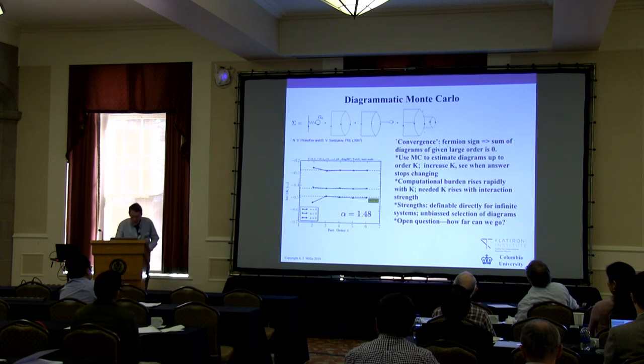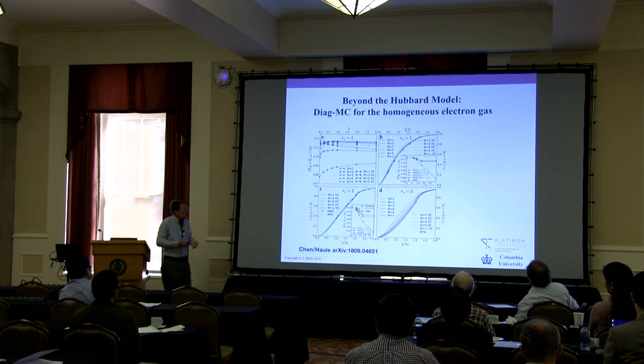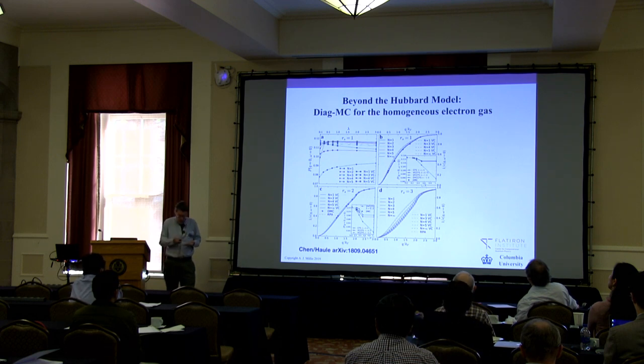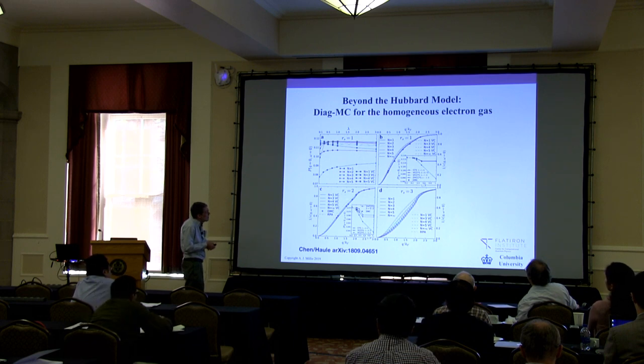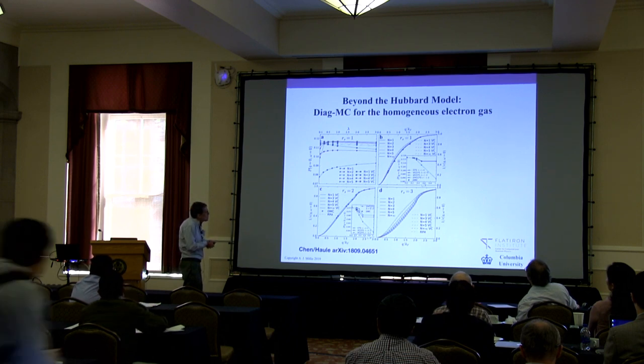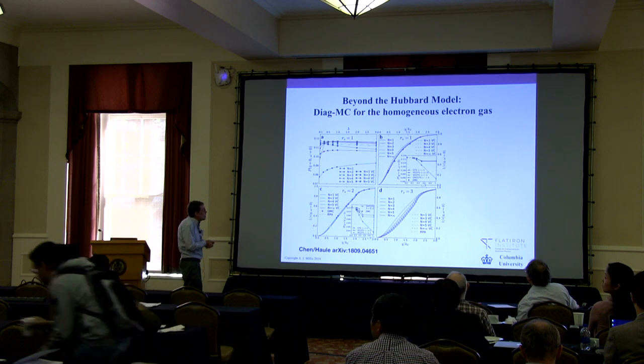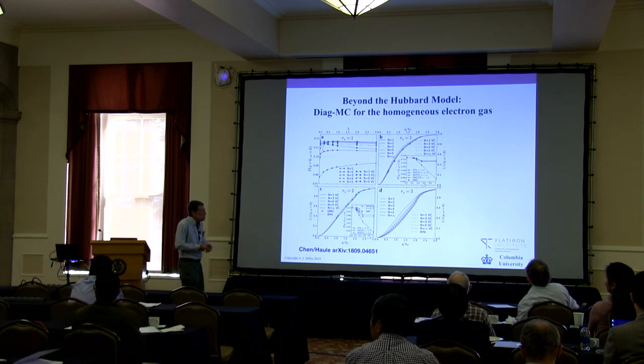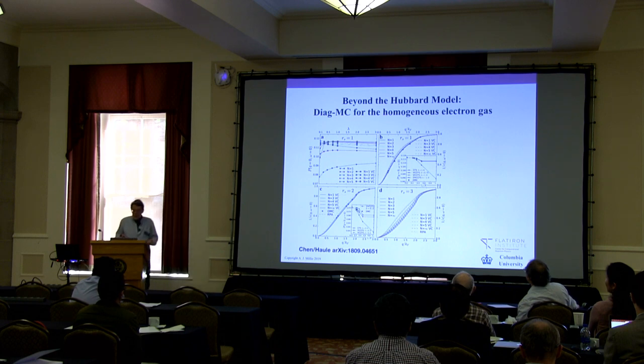All right. Now, these things were calculated for the Hubbard model, which I'll define in a second, which is a simple theorist model. This is now moving beyond the Hubbard model. Kristjan Haule and Kun Chen, in a recent paper, have shown that this works for the homogeneous electron gas, up to a surprisingly large value of the interaction gas parameter. You see here RS is 3. These n's are their notation for diagram order, all right? And these dots for RS 1 and 2 are exact answers that we have by other means. And you can see that this thing is converging, even for RS of 3, and they're now starting to claim RS of 4.